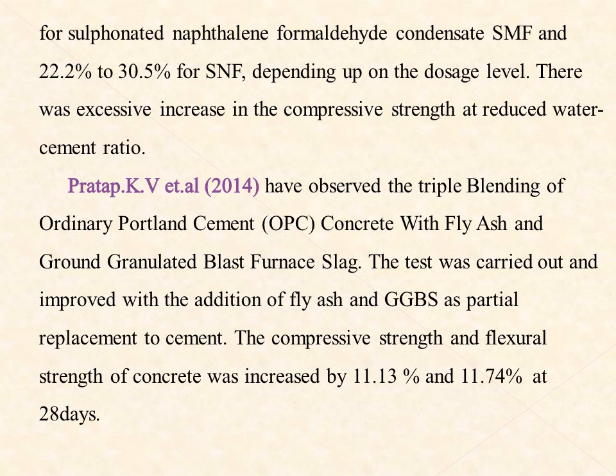Pratap KV observed the triple blending of ordinary Portland cement concrete with fly ash and ground granulated blast furnace slag. The tests were carried out and showed that the addition of fly ash and GGBS as a partial replacement to cement improved properties. The compressive strength and flexural strength of concrete were increased by 11.13% and 11.74%.